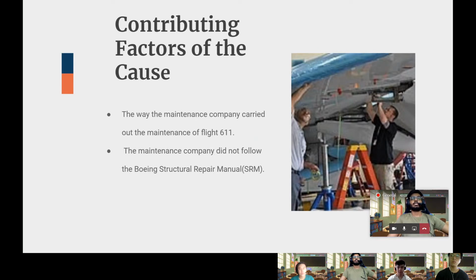After a number of pressurization and depressurization cycles during flight, cracks began to form around the exposed scratches. After 22 years, on 25th May 2002, after the faulty repair was made upon the damaged tail, the hull of the aircraft broke open mid-flight. Explosive decompression occurred once a crack opened up, causing separation of the aircraft fuselage aft section 46.